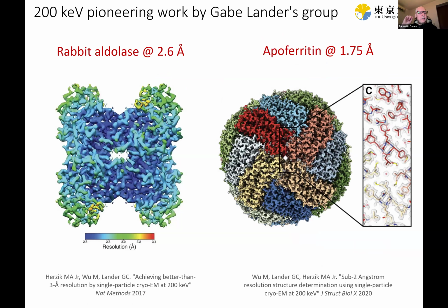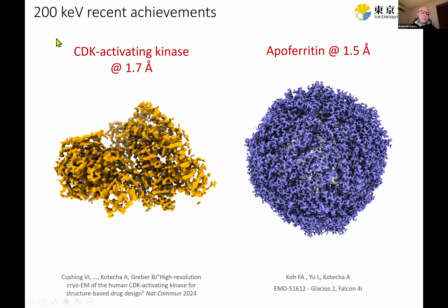Now, Gabe Lander's group was one of the pioneers that did a lot of work in pushing the performance of 200 kV machines in the past. It's almost 10 years ago, you see here. So they published some amazing structures. Here on the left, you see the rabbit aldolase at 2.6 angstrom. At the time, that was an amazing result. And then a few years later, they published also apoferritin at 1.75 angstrom. They called it Team 200, so basically people who really believed in the 200 kV machines and their capabilities. And I would now like to join this team, as you will see later. I am also a strong believer in the capabilities of more cost-efficient machines.